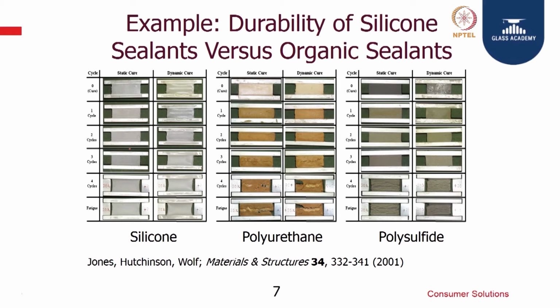So, what you tend to see is that the durability of the seal, along with taking the movement, is very critical. If you see the silicone here, the silicone was subjected to thousands of cycles on a static as well as on the dynamic cure. So, you make the joint and then cure them and then subject it to movements. You see that there was absolutely no fatigue noticed in the different cycles you have run through.